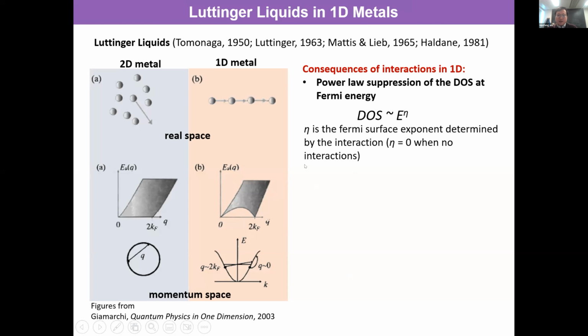And there are two outstanding, as you may already know, two outstanding phenomena. One is the power law suppression of the density of states at the Fermi surface. This means that adding an electron, for example, or a small perturbation is no longer easy. You have to pay energy. If you don't bring energy, you cannot add it; the probability for adding these electrons becomes 0, which is not the case for the Fermi liquid.